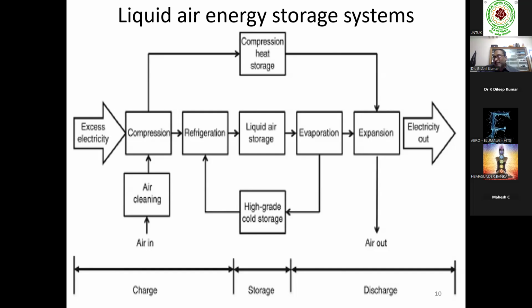Usually the storage medium can be air, nitrogen, or other. The components are air compressors, liquefaction unit, low pressure insulated liquefied air tank, evaporation unit, air expander, gas turbine, and electric generator. Cold storage and heat storage are optional. Using this, the power range that we can get is around 5 to 650 megawatts. Energy range is around 10 megawatt hours to 7.8 gigawatt hours. Discharge time is around 2 to 24 hours. Cycle life is around 22,000 to 30,000 cycles.